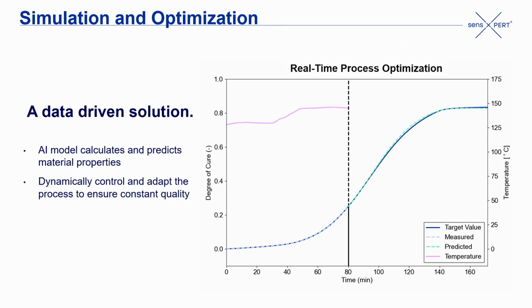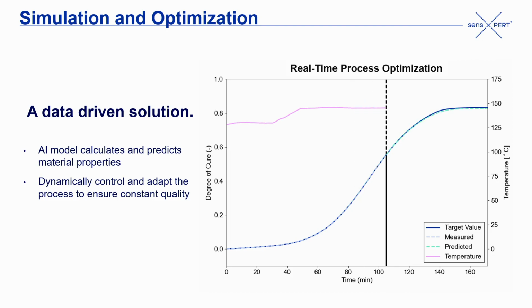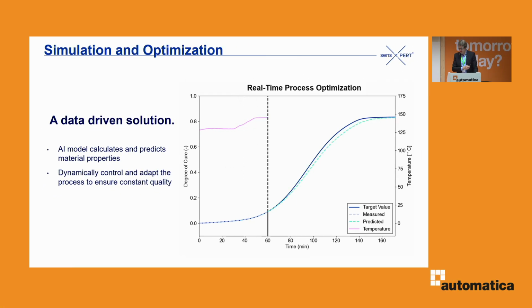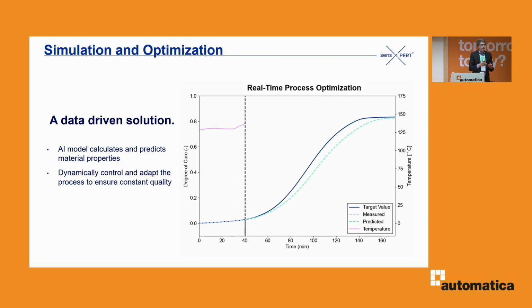And this machine learning model then allows us to not only trace the data as it occurs during production, but also to look into the future. So in this case, what you can see is the blue line, which is our ground truth, basically. So this is what really happened during one production cycle. This is the curing reaction as it happened in one part that we made. And the dashed line basically is our real time. So this is now, right? As the production happens, we are moving through time through this production cycle. And the green line, the dashed green line, represents our prediction based on what we have measured.